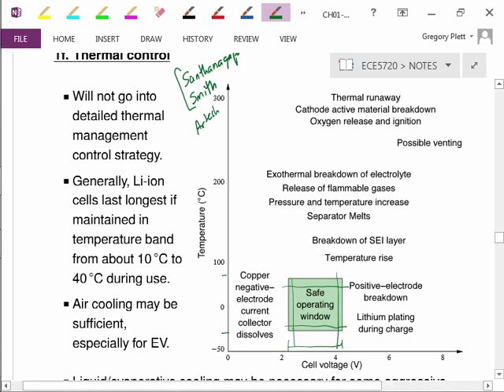There's one issue of safety in terms of whether the cell is going to catch on fire, and there's another issue of whether the cell will last for a very long time. So if you want the cell to last longer, you have narrower operating window limits. The chart, though, shows some of the things that happen if you start operating outside of those limits. If the cell voltage gets too low, the current collector on the negative electrode, which is usually made out of copper, will start to dissolve. And so you've got these copper ions floating around in the electrolyte, and they try to behave like lithium ions. They're both positively charged, except the copper ion doesn't really intercalate, and so it causes metal plating on the electrodes and starts dendrite formation and so forth. So it will eventually short-circuit your battery cell, and it's not a good thing.